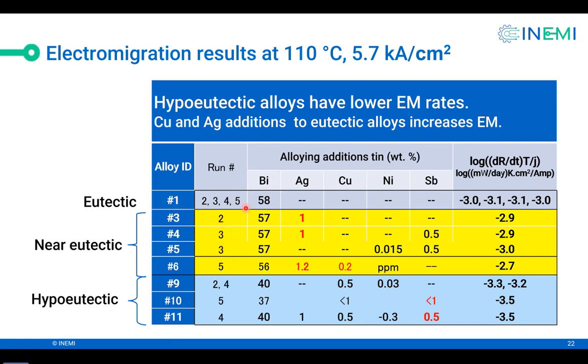Notice alloy 1 was studied 4 times. Alloy 3 was studied in run 2, alloy 4 in run 3, etc. The first run was a trial run, so I'm not showing those results. The alloying elements added to the tin were bismuth, silver, copper, nickel, and antimony. No, I'm sorry, bismuth is not the alloying element. Bismuth is the eutectic, so tin bismuth. So the alloying elements are silver, copper, nickel, and antimony.